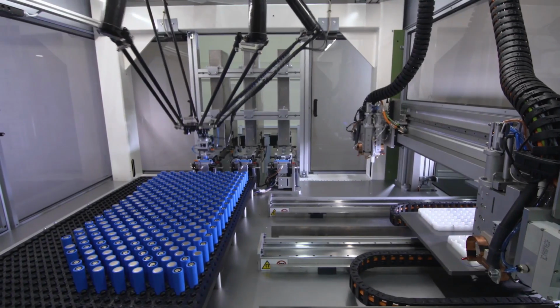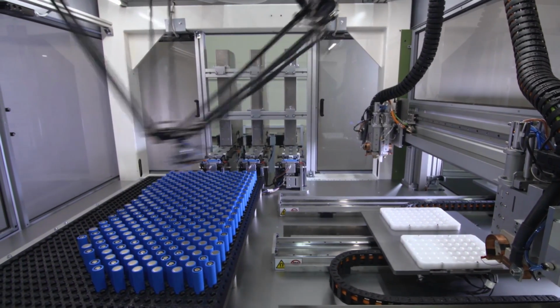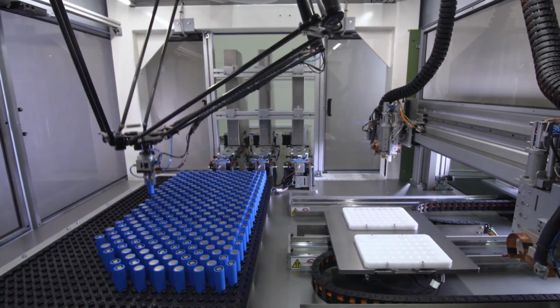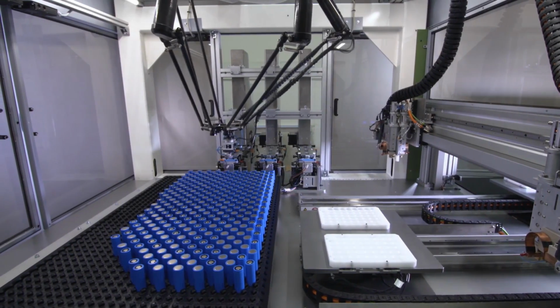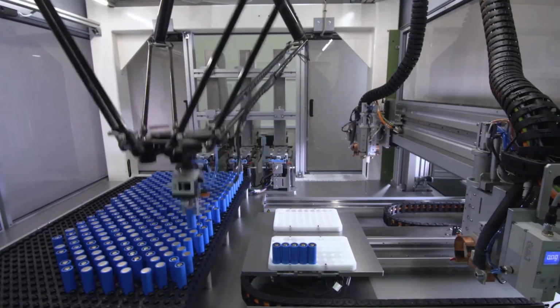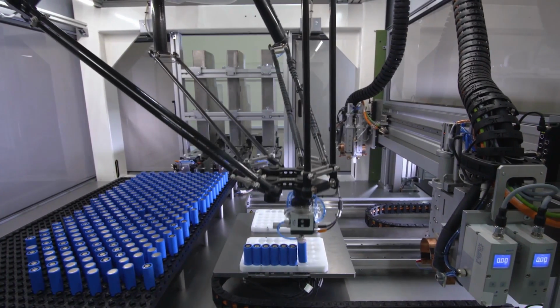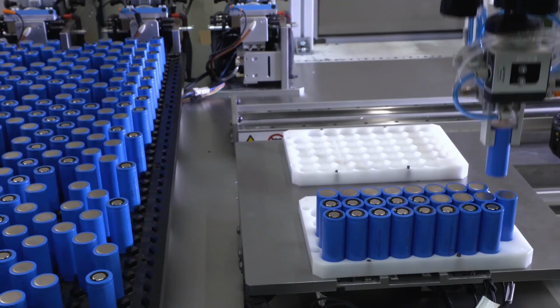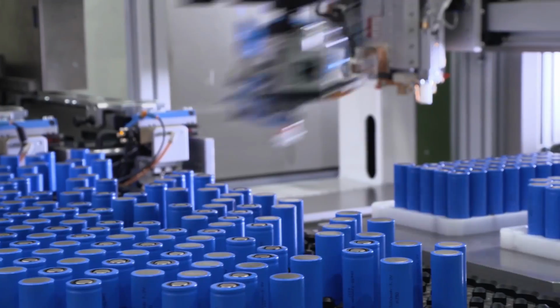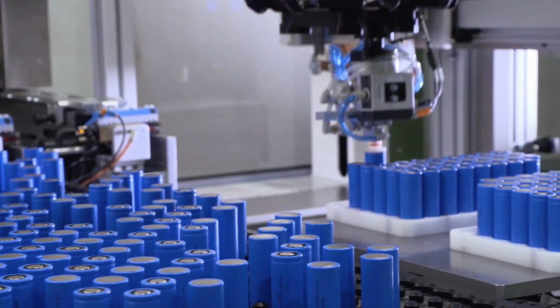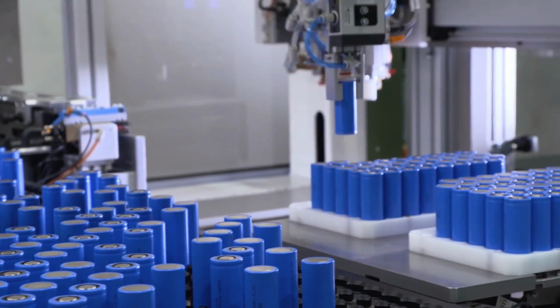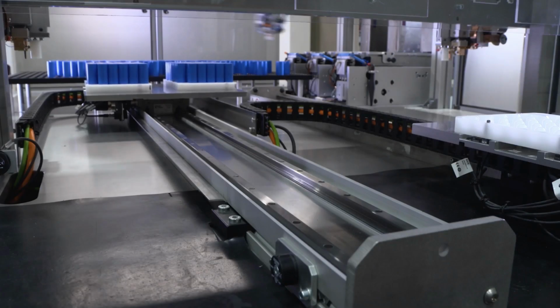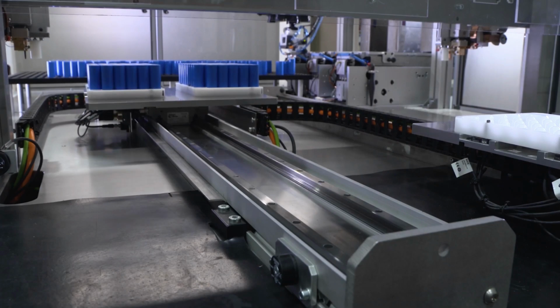However, on Battery Day, there's a good chance Tesla will unveil the highest energy density, cheapest, longest life battery cells on the market that are also cobalt-free, along with a high-speed manufacturing line. Each of these is an achievement. Bear in mind, if the Roadrunner line truly is a pilot line, it may take 6 months from Battery Day before the pilot line at Kato Road can hit $100 per kilowatt hour.